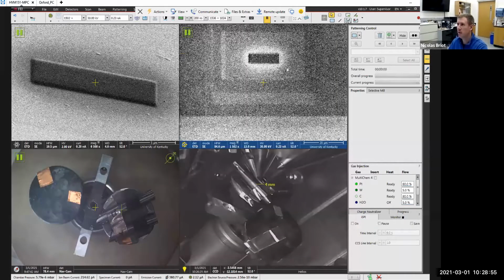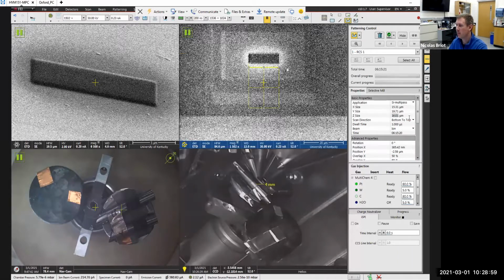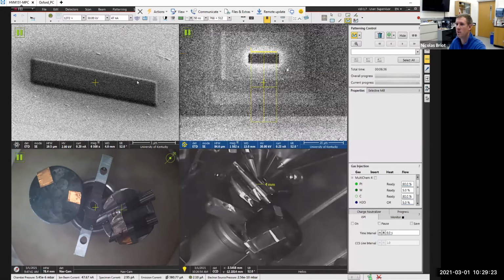So let's see, if I make the shape that I want to cut, if I want to go deep enough, and I'm not sure how deep we need to go, that's kind of the guess here. See, it's going to take 23 hours. So of course I need to bump up the current. 2 hours, I have to really bump it up. 13 minutes, that's even too much. 6 minutes, so we'll try that. You see, that's why you really need that protection. Otherwise, you're just going to blast your sample away.